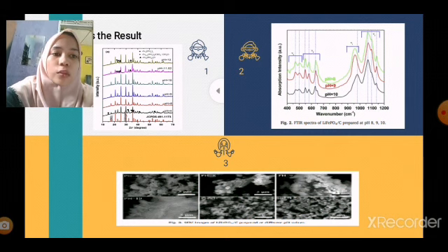The result from the FTIR spectra shows the degree of Fe antisite defects for the pH 8 and 9 samples is smaller than that of the pH 10 sample.